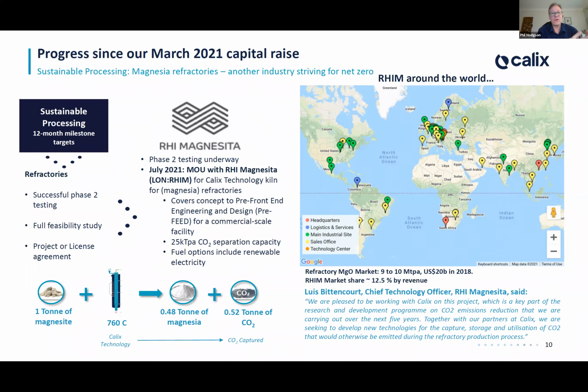You take a raw ore, in this case for the refractory industry, it's called magnesite. And again, about half the weight of magnesite is CO2 that's trapped in that rock in the form of what's called a carbonate. And when they heat that up, in this case, it's about 760 degrees they've got to heat it to. They get their magnesia, roughly half the ton, but the other half the ton is CO2. So the refractory industry is under incredible pressure as these CO2 penalties start to come in around the globe. Under incredible pressure to try and decarbonise.